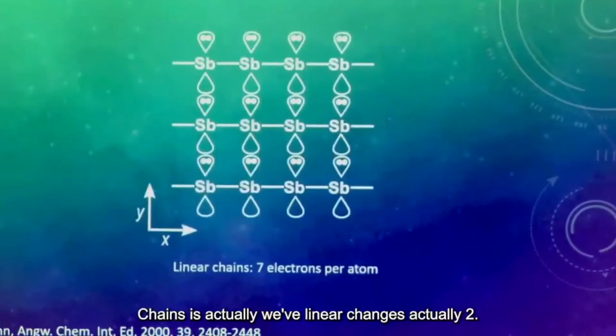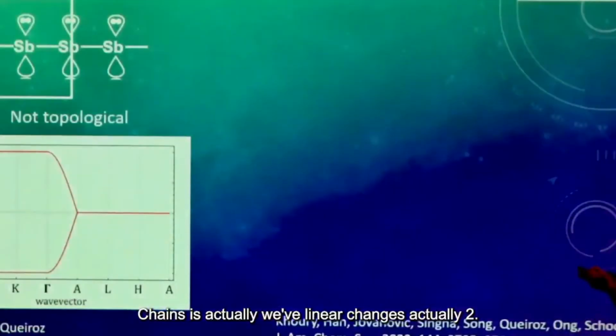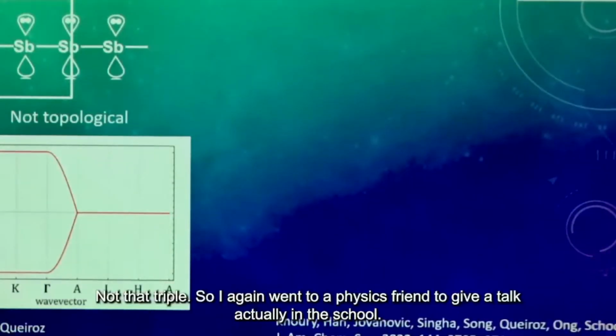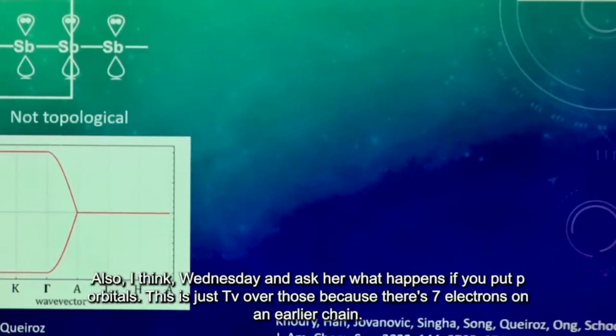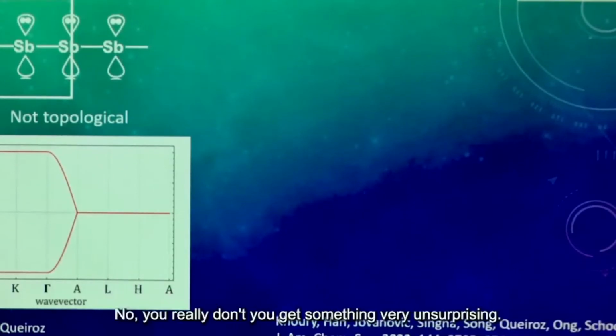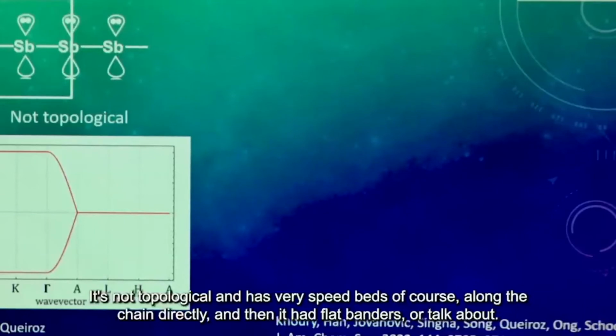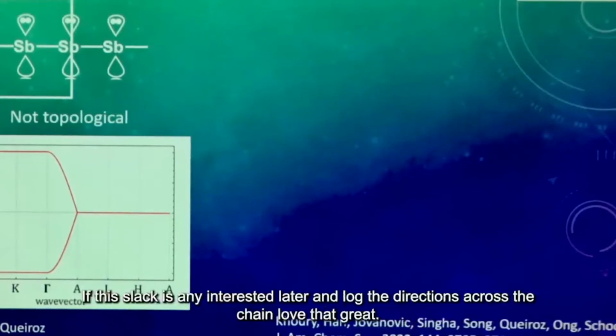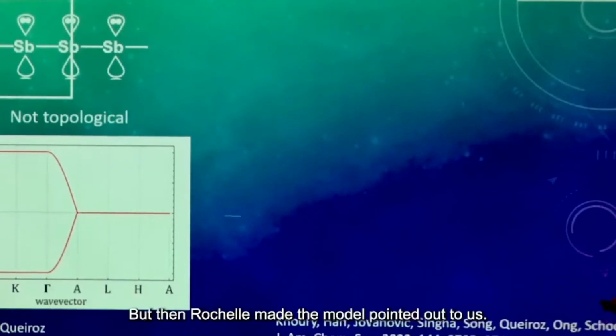But with linear chains, it's actually not that simple. So I again went to a physics friend, who gave a talk in the school also, I think Wednesday, and asked her what happens if you put p orbitals, just pz orbitals because it's 7 electrons, on a linear chain. What's the band structure? Do I get something topological? You shouldn't be surprised. No, you really don't. You get something very unsurprising. It's not topological. It has very steep bands, of course, along the chain direction, and then it has a flat band, and we'll talk about if this flat band is interesting later. Along the directions across the chains are not that great.